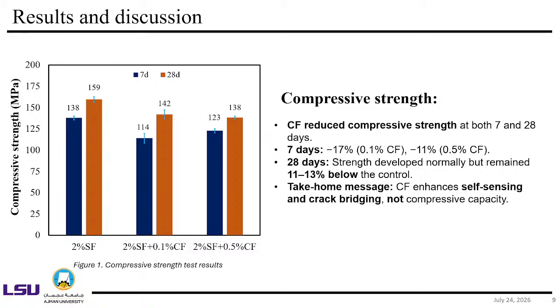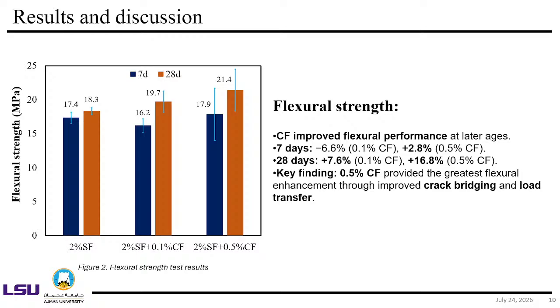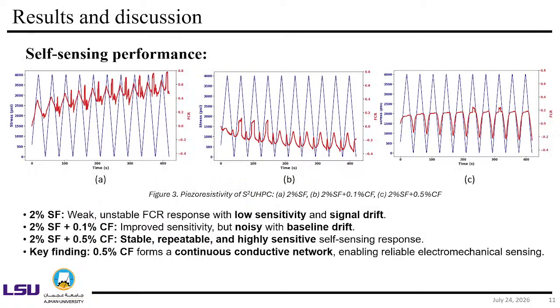For compressive tests, we are looking at this orange, which is 28-day strength. With more carbon fiber, it actually decreased, which is not unexpected. I'm going to explain it later. For the flexural strength, with more carbon fiber, it actually increased, because those carbon fibers help with crack bridging and load transfer. So that's a good thing. Flexural strength increased.